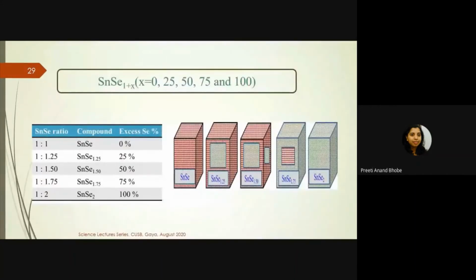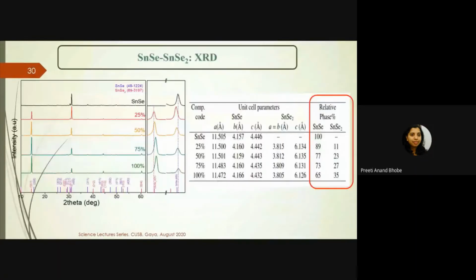And what we did was we prepared SnSe, we prepared SnSe2, and we tried to have the ratio in between changed. So you take a pure matrix of SnSe, then you put in some SnSe2, and then a little more, and then a little more, and then your aim is to make 100% SnSe2. When we tried to prepare this in the lab, we realized that pure SnSe gets formed, and then as you put in 25% excess Se and then 50% excess Se, you start getting the SnSe2 phase. The other phase starts coming here, the small peak which is shown here.